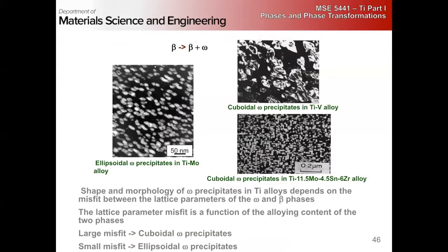It's just the anisotropy of the crystal. So you can have planes that are lower in energy than others, so you will tend to grow to maximize the amount on those planes. Essentially, if you have a cuboidal particle, you can think about the cube faces of the BCC being a much lower energy than other planes.